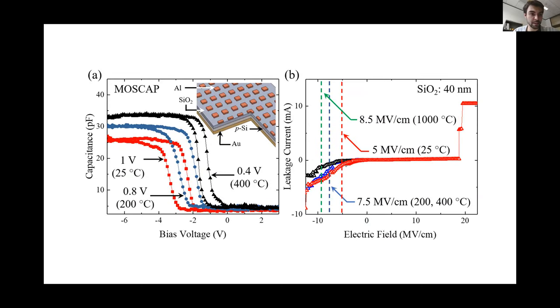We did some electrical tests, so I would like to point your attention to the right-hand side of the slide. The breakdown voltage of a 40 nanometer SiO2 film deposited at 25C was measured to be 5 megavolts per centimeter. And this is a really impressive number for 25C because the best that we were able to get with dry oxygen at 1000 C is 8.5 megavolts per centimeter. So this tells us that the films are actually high quality. They are dense, non-porous, and our analysis shows that they are stoichiometric, so they are pure SiO2 films.